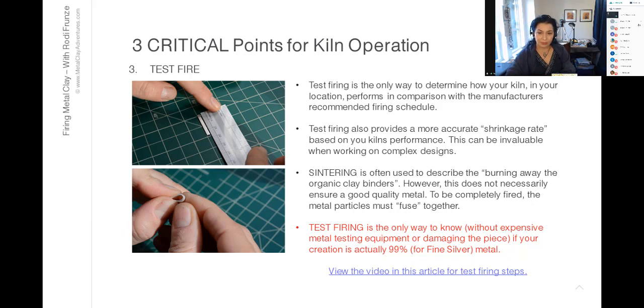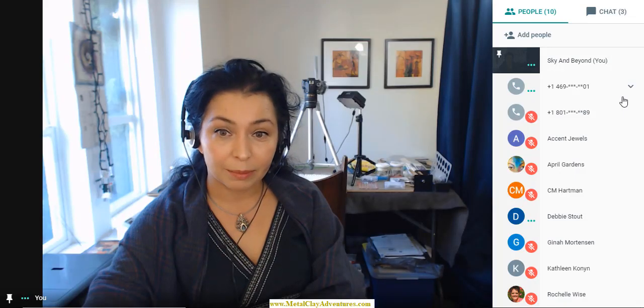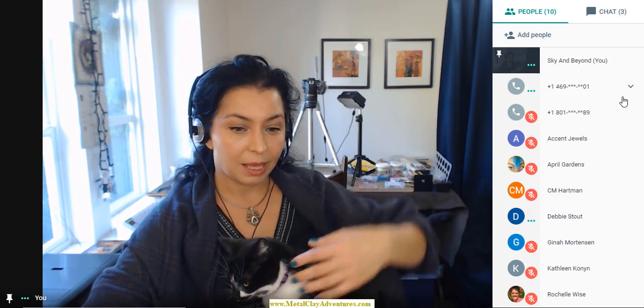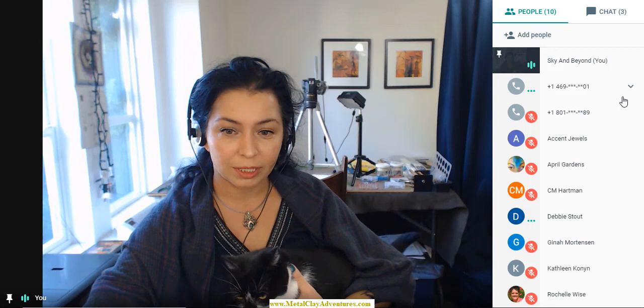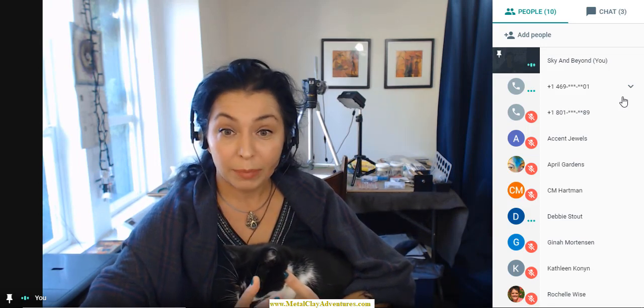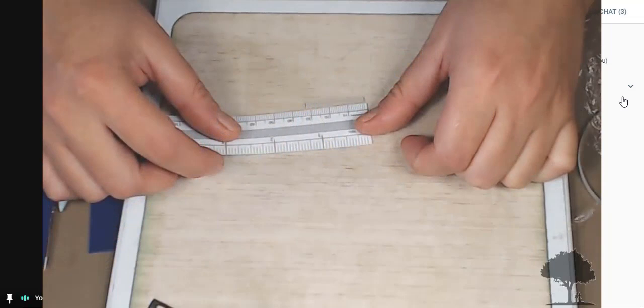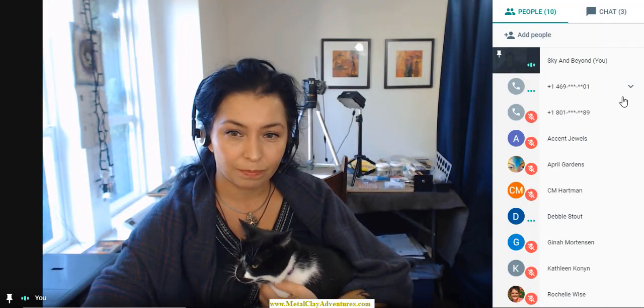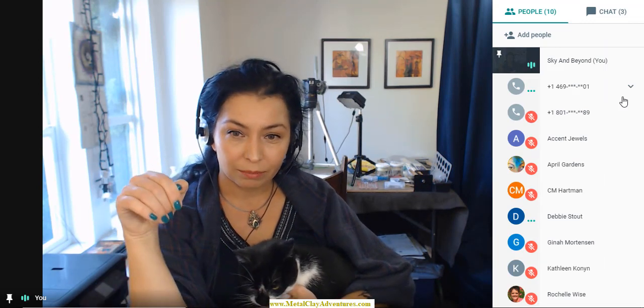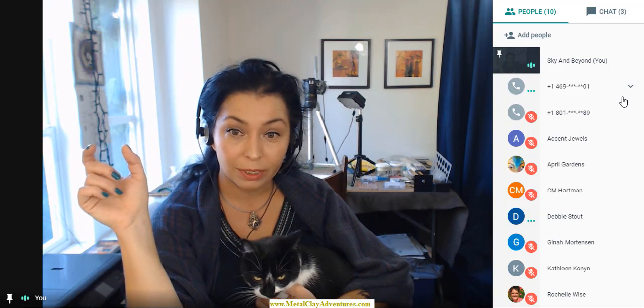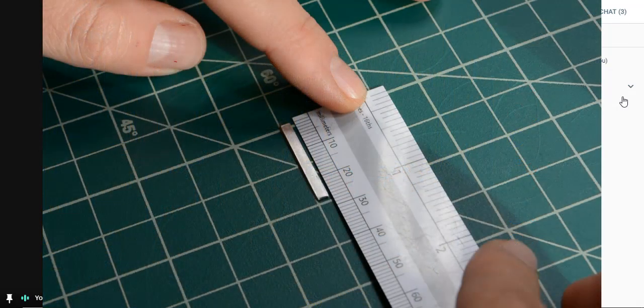I am cutting my strips 4 cards thick and drying them completely before test firing, and placing a strip on the medium you are test firing on, and measuring the strip before placing it in the kiln, and after running the kiln for the temperature and for the time you need to sinter it. We are getting the strip from the kiln, and the first thing we are doing, we are measuring it again, and having the measurements before firing and after firing, we are calculating the shrinkage. So when test firing, the first thing we are looking for is shrinkage.